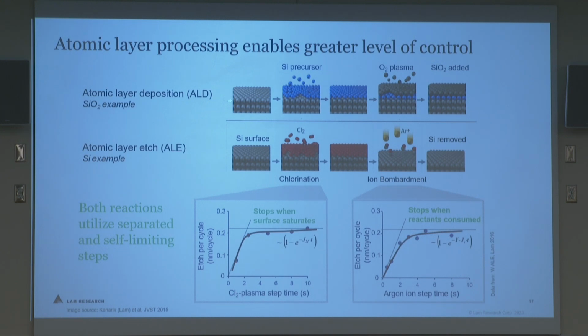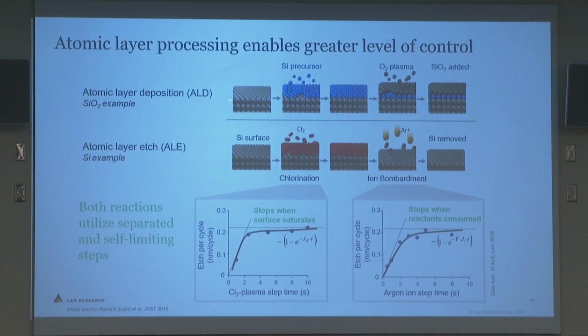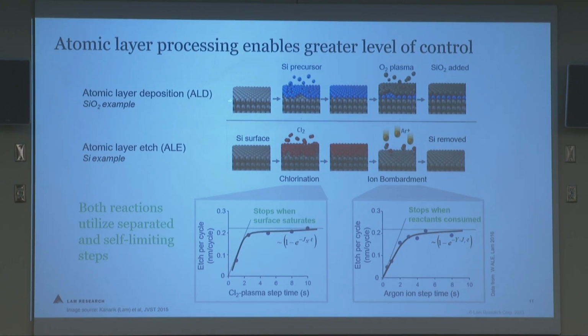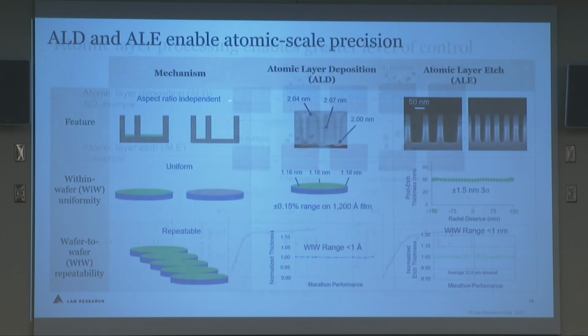It's the same etch per cycle now, but we're looking at the argon ion step time. And again, you can keep bombarding it with argon, but we've tuned in that energy level that will only remove what was reacted with chlorine. So when you remove that atomic layer, it just stops and nothing else gets removed. And this gives us really precise control and a lot of other advantages.